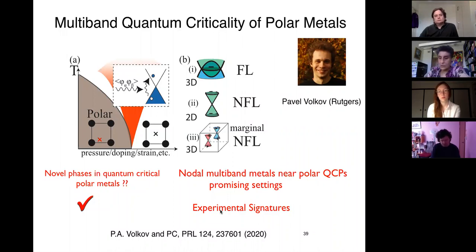In each case, the critical polar mode is strongly renormalized. You get unusual dispersions, and there are a number of interesting points that crop up. Again, this is in this paper. And the good news is there are already a number of polar metals with multiband structure. For example, tungsten ditelluride, molybdenum ditelluride, lithium osmium oxide, and many more that are predicted. So we're hoping that this will be a new setting to look for novel electronic phases.